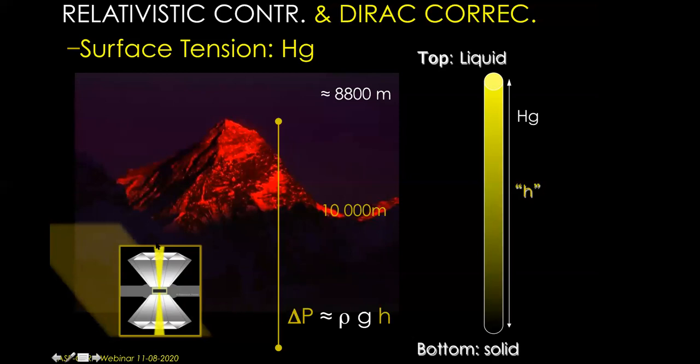And after that, we come with an X-ray beam from a synchrotron source or a neutron beam from a nuclear neutron research reactor. And we probe this squeezed mercury, and we will see a diffraction pattern, and we would know at what pressure exactly this mercury, which was liquid, becomes solid, if we see a pattern. Now this is expensive, of course. You need to access a synchrotron, you need to access a neutron research reactor,